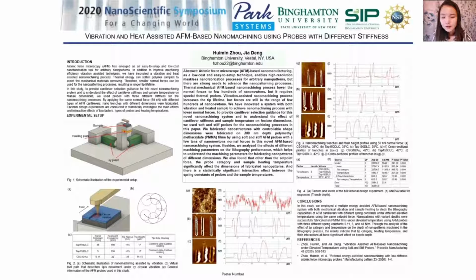As you can see in Figure 4A, in the full factorial design experiment, the first factor, tip category, has 3 levels, and the second factor, sample temperature, has 2 levels. Generally, the result shows that trench depth of the stiffer tip is larger than that of the softer tip for both temperatures. Figure 4B shows the ANOVA table of the factorial experiment, and the p-values of both factors and their interactions are all zero, indicating that the tip category, heating temperature, and their interactions all have significant effect on trench depth.